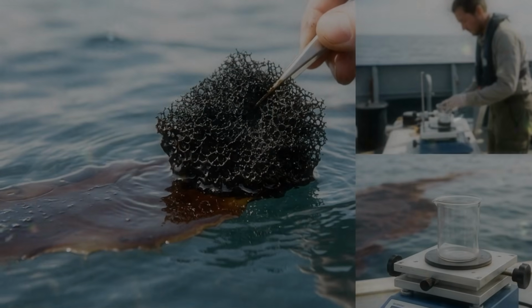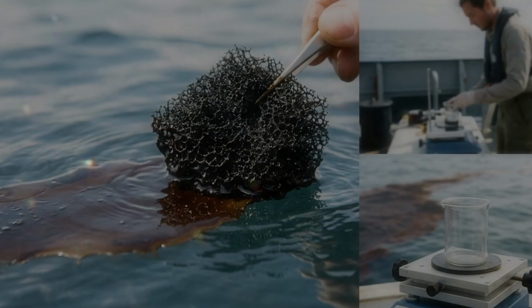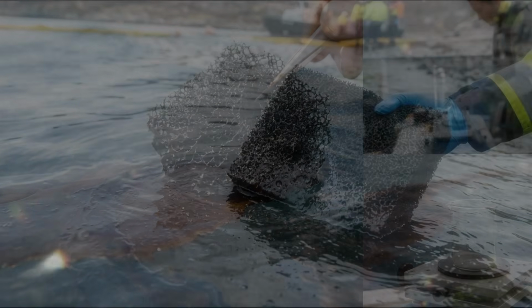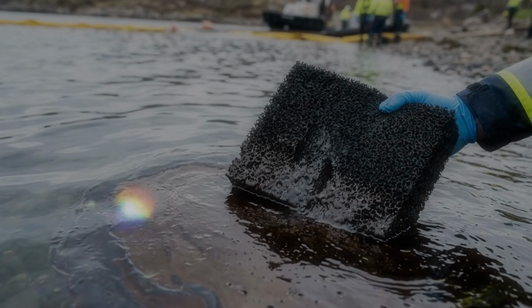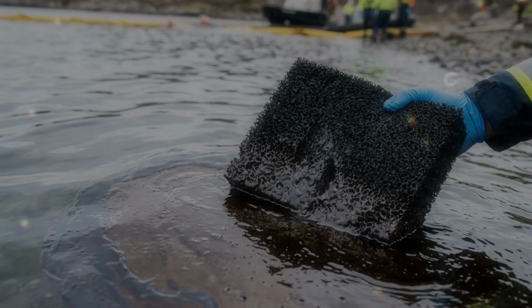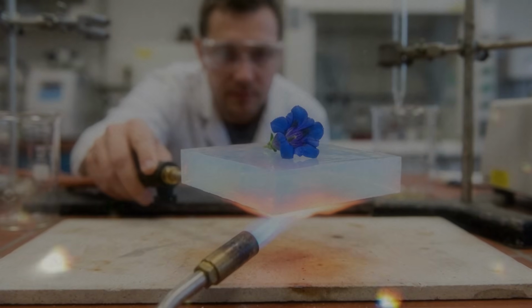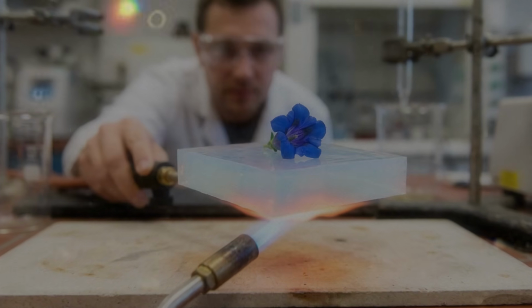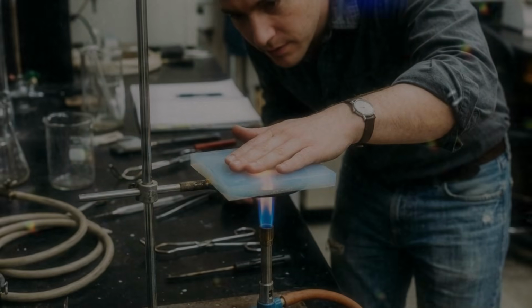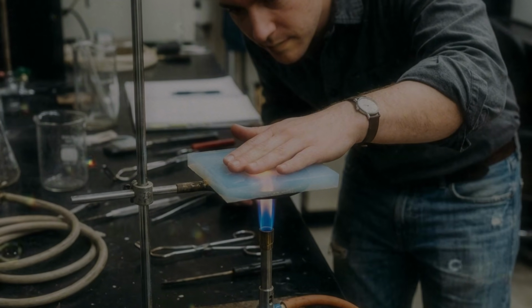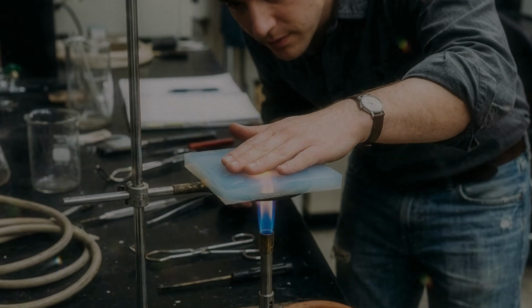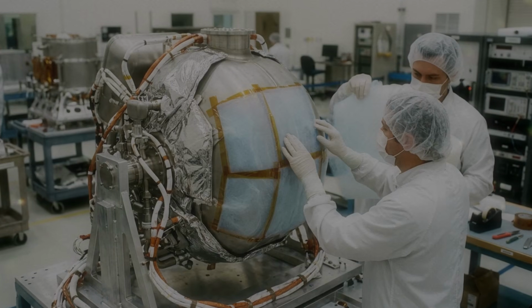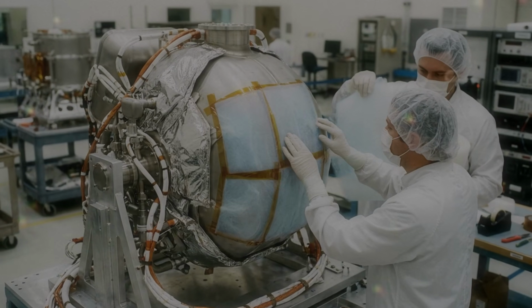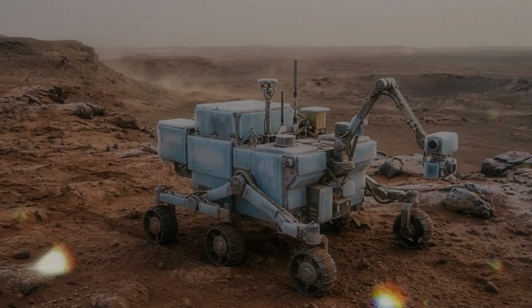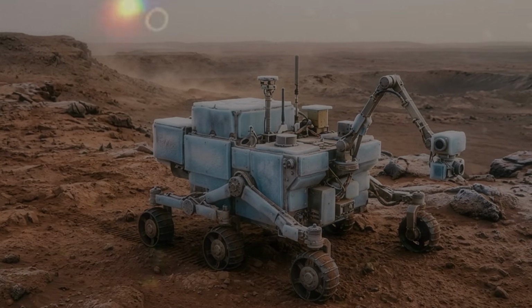No matter which route is chosen, the finished density depends on how much solid material was present in the starting mixture and how much the network shrank during drying. A dilute mixture can produce a lighter aerogel, but the connections may be weak. A concentrated mixture produces thicker walls and greater strength, along with more weight. The challenge is not reaching the lowest possible number. A record-setting sample may be too fragile for practical use. It may survive only when handled with extreme care. An engineer designing an electrode, insulation panel, or spill absorbent may accept a slightly higher density in exchange for durability.